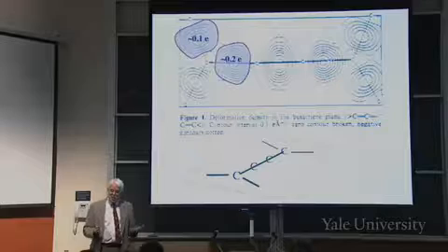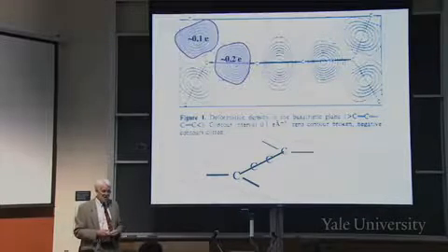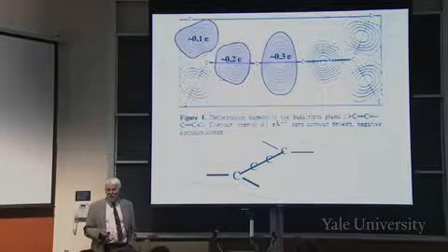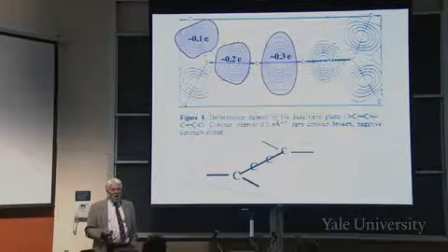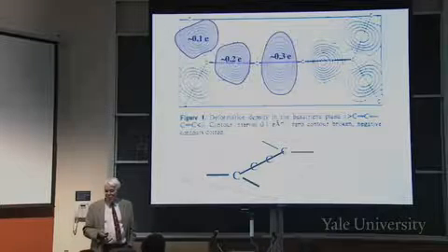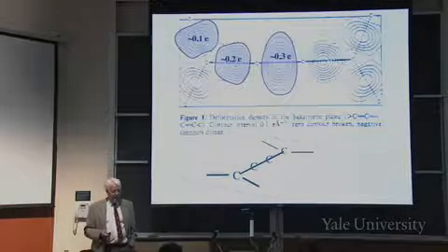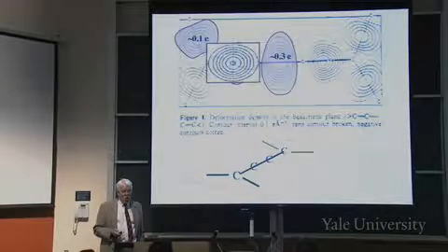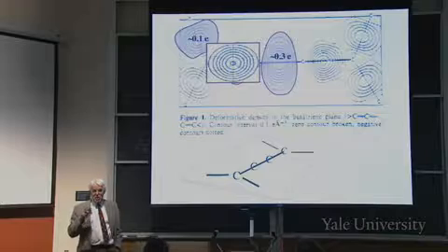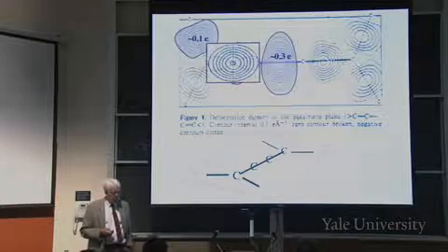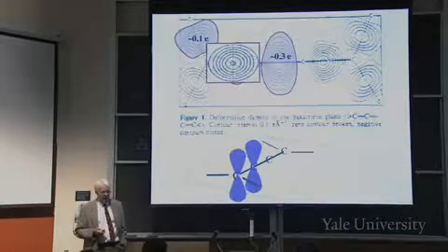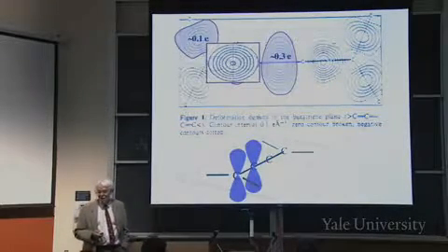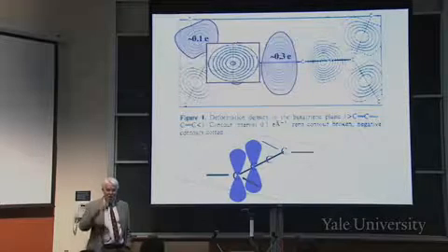Not too surprisingly, it has more electron deformation density in it, 0.2, right? And the one in the middle actually has 0.3. Now, they're both double bonds, so probably they look similar, right? And in a sense, they do. If we slice the first one and turn it, it's oval for the same reason as before. There's a p orbital pointing in and out of the board. And if we look at it below, part of the bond is caused by overlapping, as we'll see, of those p orbitals. So it's got an oval up and down shape.